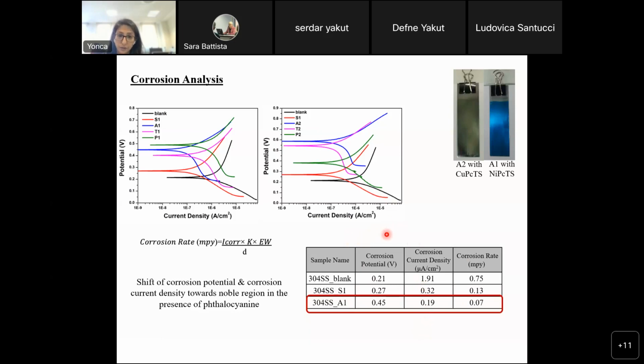Although the tetralayer structures also shift to more noble regions, in the presence of phthalocyanine they don't show any significant change in corrosion rates. So actually, what we can say is, yes, they help to protect the underneath surface, but not always. The studied architecture also plays a role. So you have to make sure that you have the desired concentration of phthalocyanine, pH, and also the architecture is highly significant to have a proper protection.